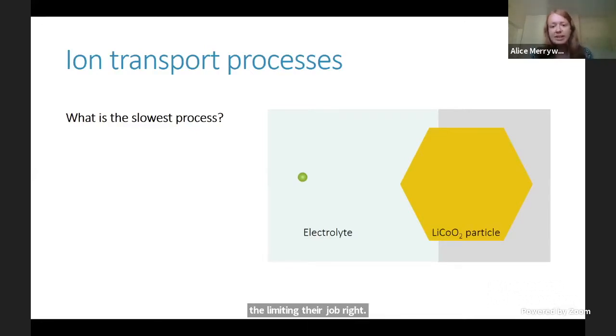So we can break down several different fundamental ion transport processes which might be limiting the speeds that the electrodes can operate at. Imagine this yellow hexagon that I'm showing you here is a little particle of material that can store the lithium ions, for example, that lithium cobalt oxide that I already mentioned. One battery electrode is going to contain millions of these little particles of active material.